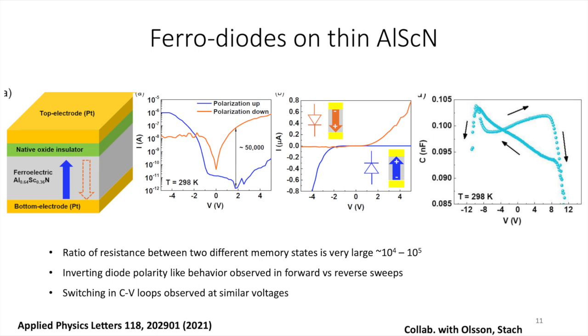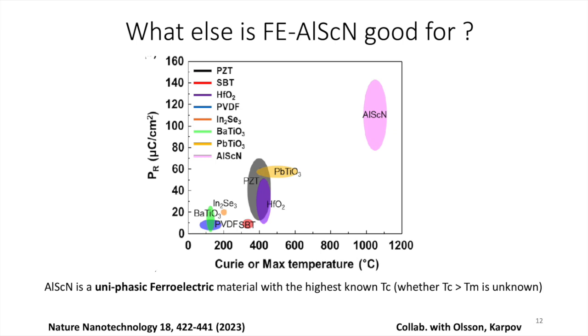And the new stuff is, what else is aluminum scandium nitride good for, which is what is mentioned on slide 12. Actually, there's another thing where the material stands out quite dramatically, which is if you look at the remnant polarization of the material as compared with the maximum temperature or the Curie temperature of the material, you see that it's at the top right corner, which means it's one of the most stable yet most polar ferroelectric materials that we have found.